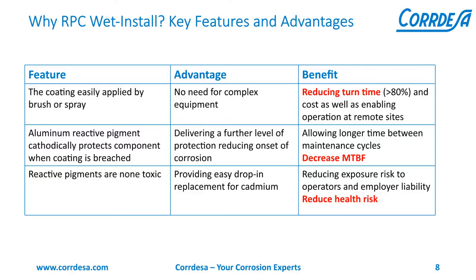Why should you use a wet install RPC system? Well, here are some reasons. The coating is easily applied, brushed on, or sprayed on just like paint. There is no need for any expensive or complex equipment or special plating facilities. This significantly reduces the turn time by a large fraction, more than 80%. And you can perform the repair in forward locations also. The aluminum reactive pigment coating protects a component even when the coating is actually breached. So when areas of the coating are damaged, the protection is ongoing, resulting in longer times between maintenance cycles. Also, the reactive pigmented coatings are non-toxic, providing a safe replacement for cadmium, reducing exposure risk to our operators and ensuring their ongoing health and safety.